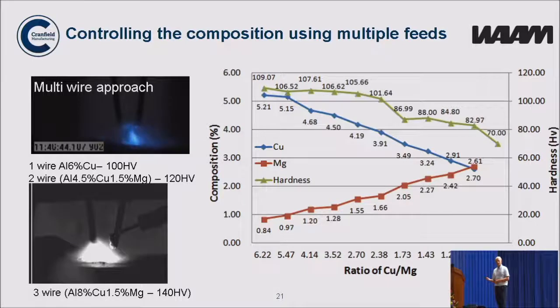And in fact, you can take that further as well. This is using 3 wires. Because the aluminium copper wire is limited to 6%, if we want to get the copper higher than that, then we would use a 3rd wire. And in this case, we achieved 8%. And you can see the increase in hardness.